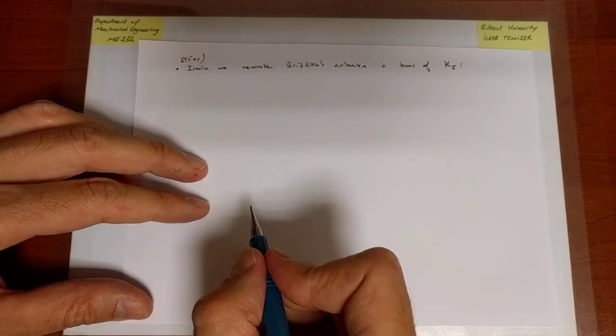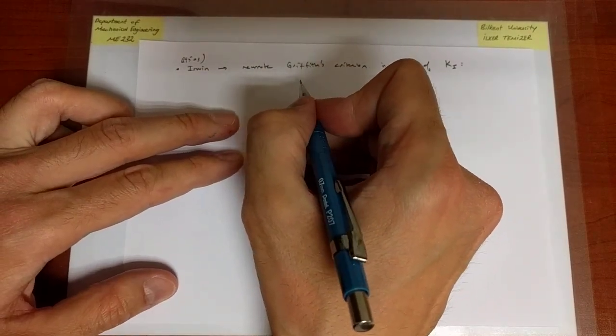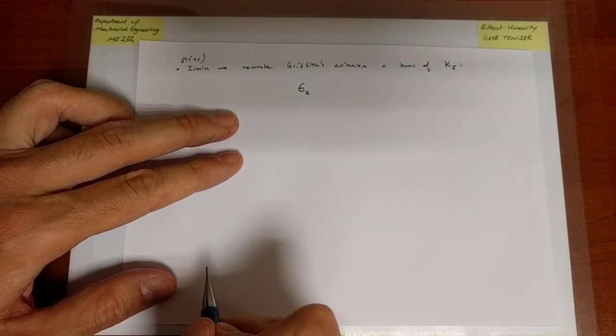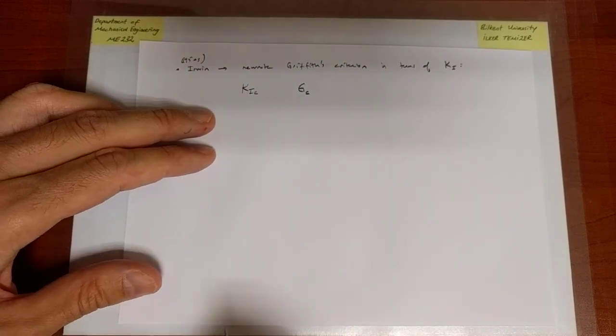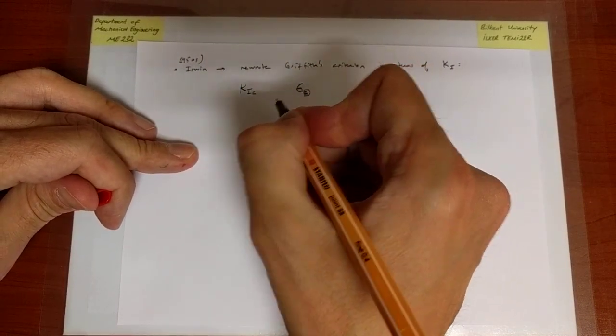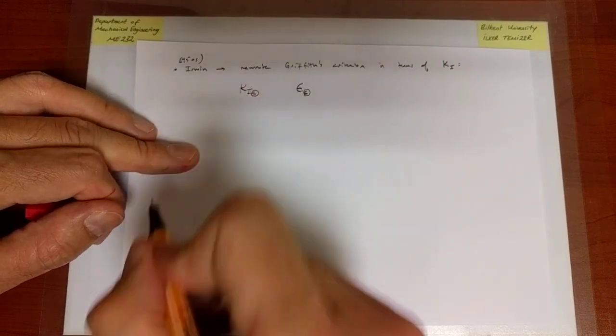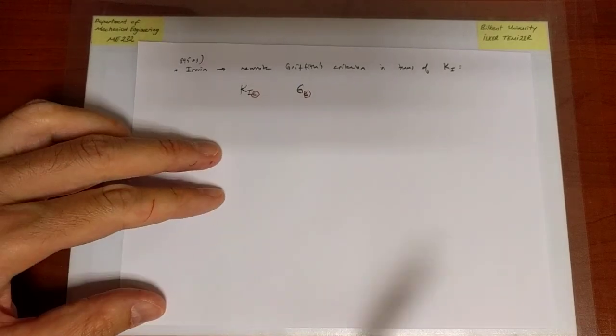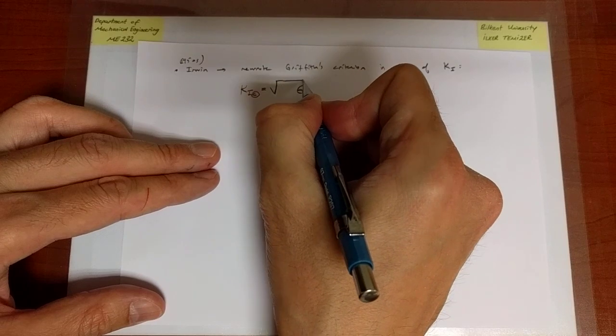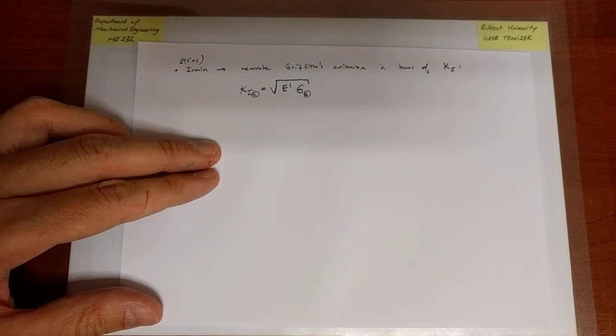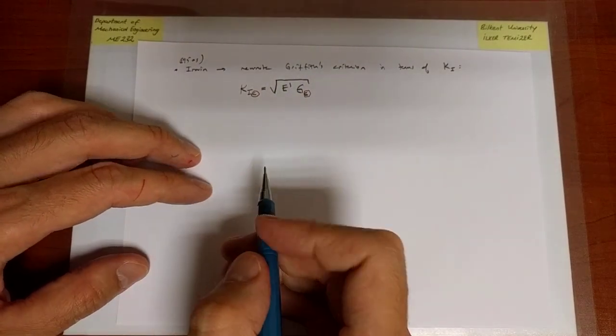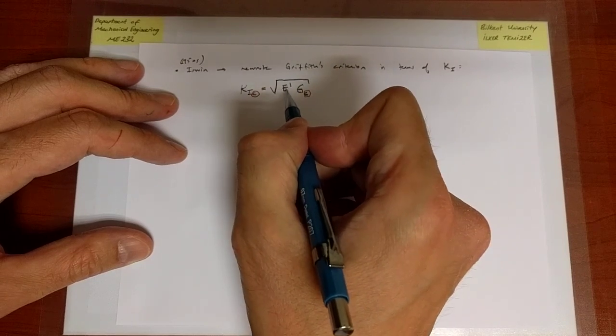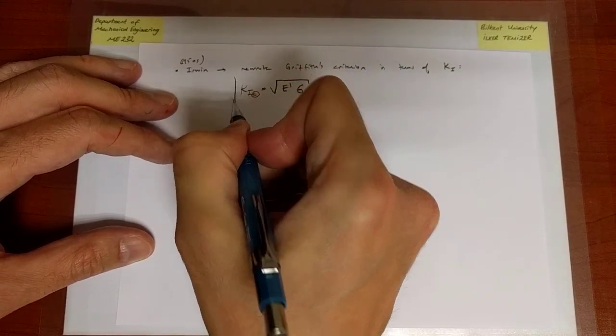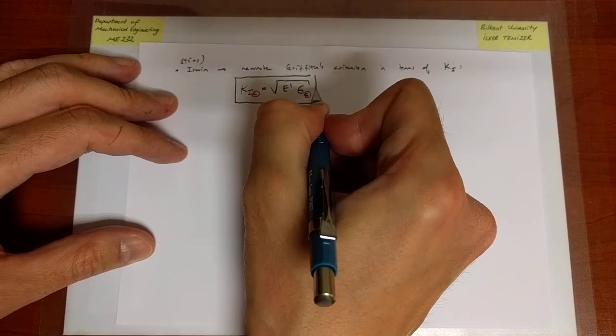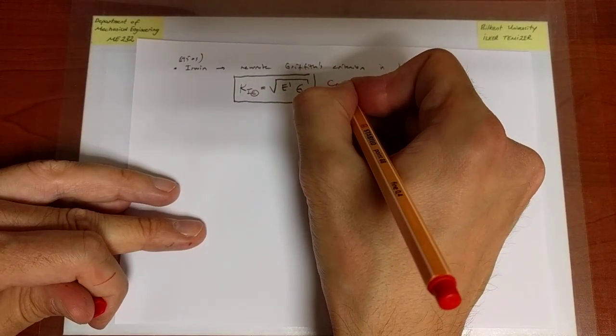So what Irwin did was, first of all, he said that, well, there is a relation between the critical strain energy release rate and a critical amount to which the stress intensity factor must reach. So here I am putting a critical symbol C on G, I'm also putting a critical symbol on K1. And the relation physically is equal to square root E prime. So not the Young's modulus, but very close to the Young's modulus. I'll make a note of it very soon. And so you can take G and multiply it with E, take the square root, and boom, you have a value, the so-called critical strain energy, the critical stress intensity factor.